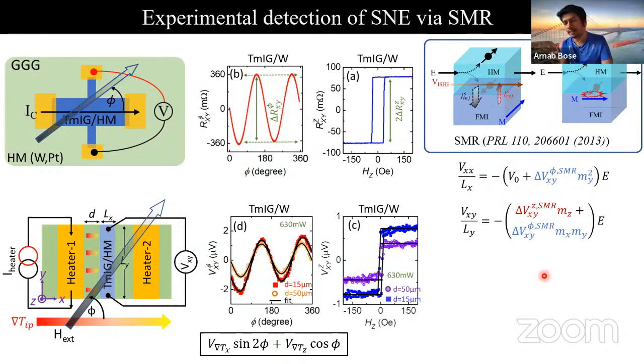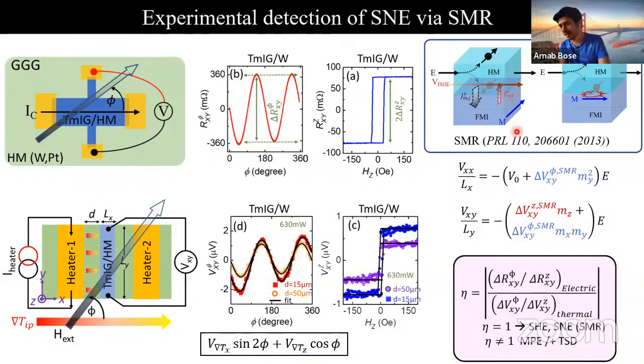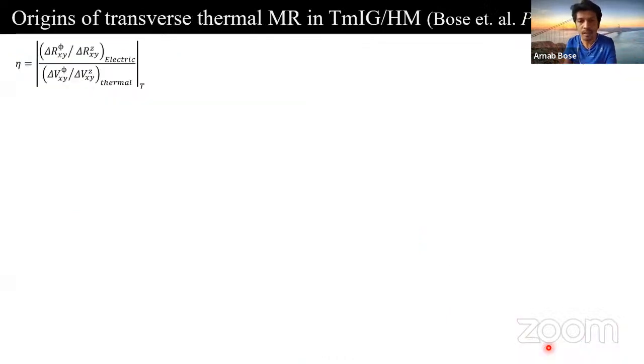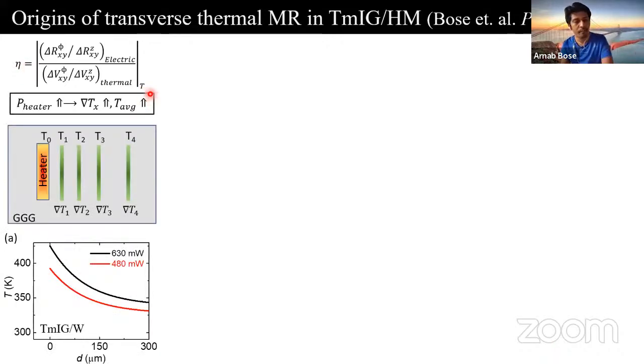Okay, so we find that if the origin is spin Hall effect and spin-Nernst effect, just doing some simple calculation, we find that if we take the ratio of this transverse magnetoresistance driven by electric current and thermal gradient, then it should be strictly equal to 1. This is something we want to experimentally investigate. If this is not equal to 1, then there must be some other origins which we need to figure out. So we have to evaluate this parameter eta for a given temperature.